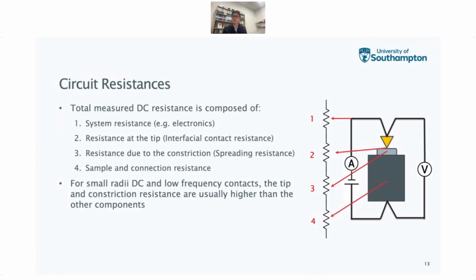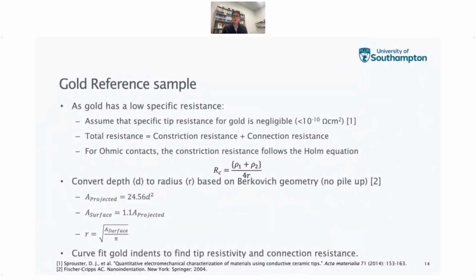So generally for small radii contacts, when you're doing very small nano-indentation type of contacts, DC and low frequencies, usually the tip and the constriction resistance are the higher resistive components. And so what we can do is we can start then probing something that is well characterized, such as gold. We can insert our tip into gold, which has a very low specific resistance, such that we might be able to neglect the tip resistance because it's very low. And so our total resistance then becomes a sum of the constriction resistance and the connection resistance, everything else. And then if you're in the ohmic contact region, you can then model the constriction resistance as part of the Holm equation for the two materials in contact, and that's the sum of the two resistivities divided by 4 times the radius of the contact.